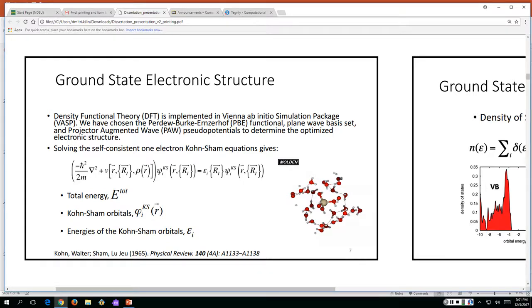So the simulation models are shown on the left for the vacancy model. The two-dimensional slice shows a missing lead atom, which is removed from the system. And in the three-dimensional image, it would be right in the middle of that simulation cell. And so by removing the lead atom, it produces a number of interesting electronic environments. The removal of the lead also removes 2 valence electrons, which need to be replaced into the system for the calculation. So we have a perfect system for one. Our second system just has the lead removed and no charge correction. The third system has 1 electron added back in, and then the other system has both valence electrons added back into the calculation.